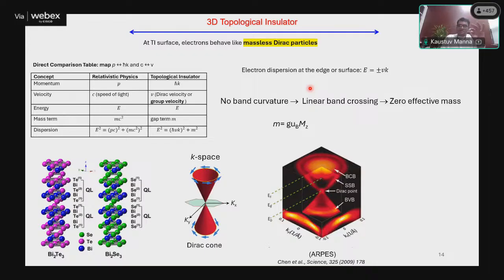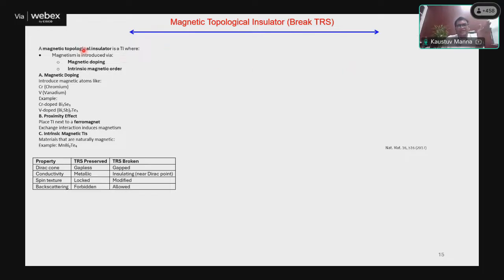Now what happens if you break the time reversal symmetry? This is the scenario for a magnetic topological insulator, where you can do it by magnetic doping, or you can have an intrinsic magnetic order. Examples are chromium or vanadium doped bismuth selenide or BiSbTe3, from the experimental reports. Or you can break time reversal symmetry by the proximity effect. Let's say you have a topological insulator and you deposit one layer of ferromagnet, so that through the interlayer exchange interaction, the ferromagnet can induce spin polarization into the topological insulator. Or you can have a compound, a very rare coincidence, for example manganese bismuth telluride.